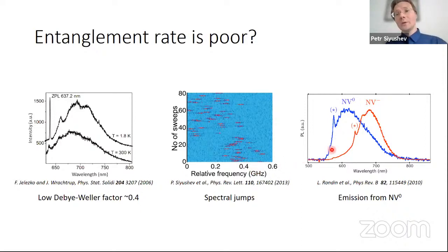And the next problem is that the nitrogen vacancy center has two different charge states, well, at least two different charge states. And while preparing any sequence, you always need to either initialize or probe your charge state before running. Otherwise, you might simply end up in another charge state, and your protocol, your single run, will be useless.